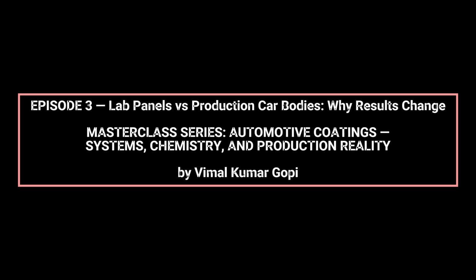Laboratory-to-line translation is also affected by process variability. Variables such as spray gun distance, atomization pressure, line speed, ambient humidity, and solvent blend interact with the coating's inherent properties to magnify minor deviations, often resulting in OEM validation failures that were not predicted by lab tests.